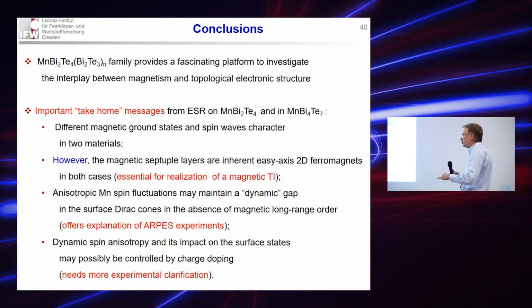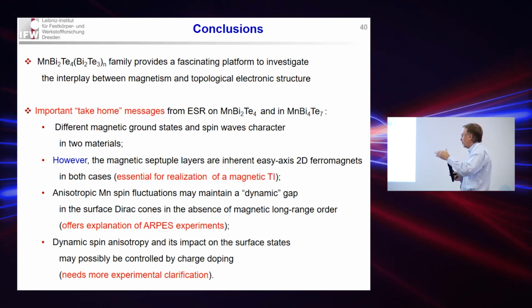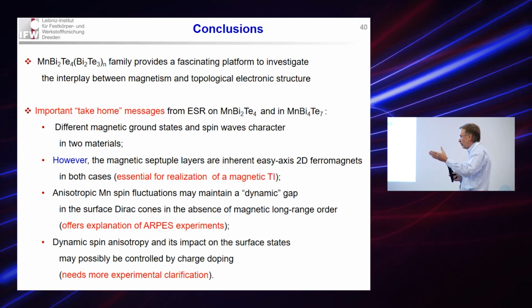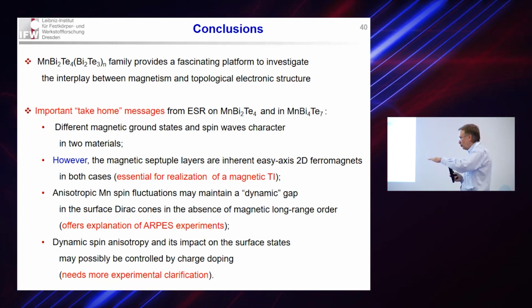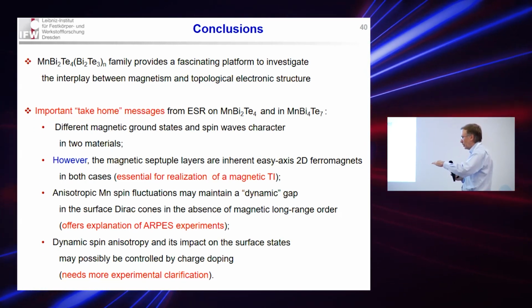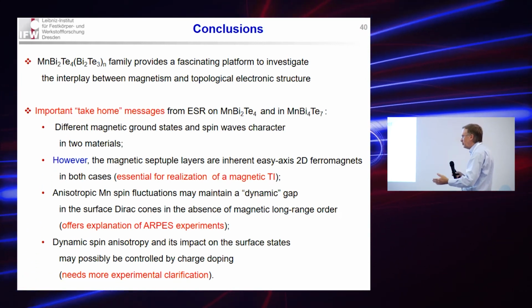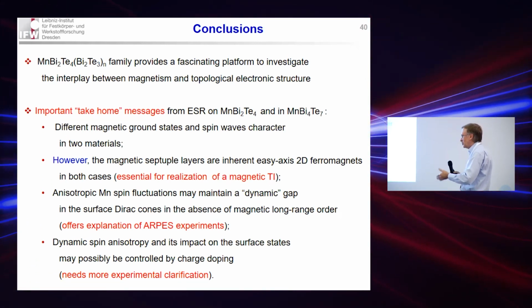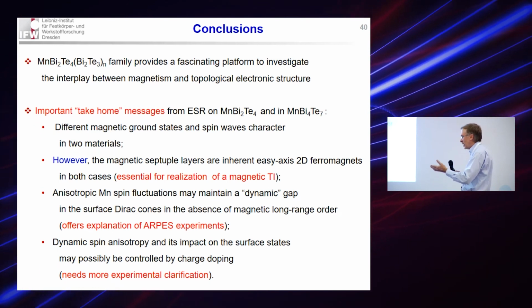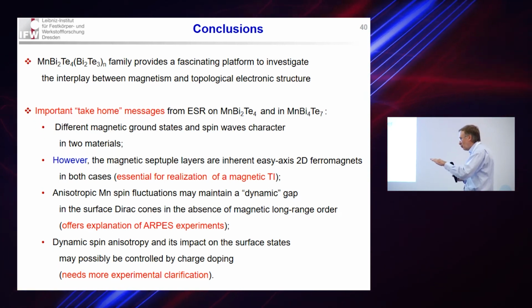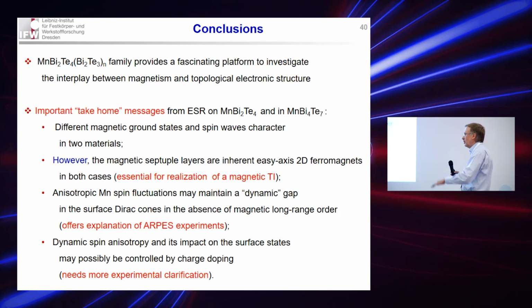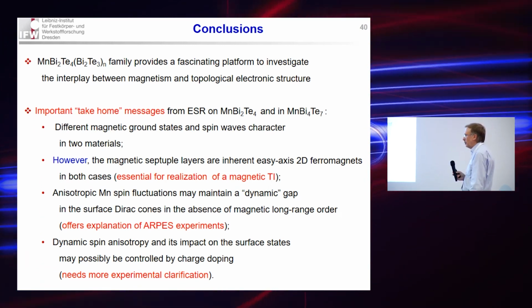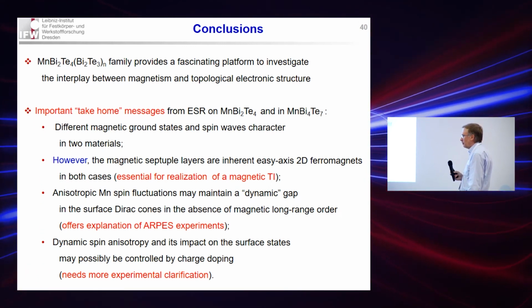And that is clear because in the bulk you have many magnetic layers which are antiferromagnetically coupled. But as soon as you reduce the number of layers, the probability that you find a flake which has an odd number of magnetic layers is high, and therefore in this sample you could see it really very nicely. So these are very thin samples, nanometers, something like that.